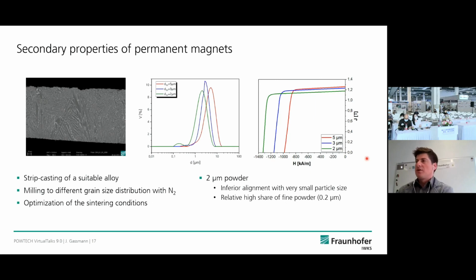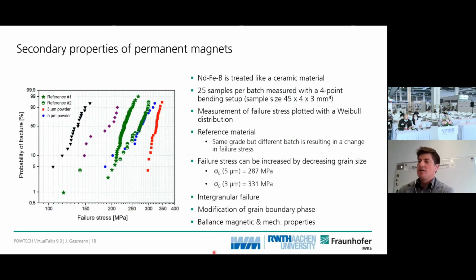For us, what was important, and this analytics was done by our colleagues from Aachen in this project, were the mechanical properties. So we measured the failure stress of the material with a four-point bending setup. First, we did it for commercial references which the customer used for his application. It was the very same grade from the same supplier, but different batches. And here in green, one can see that the 25 samples for each batch we measured show different properties in terms of failure strength.